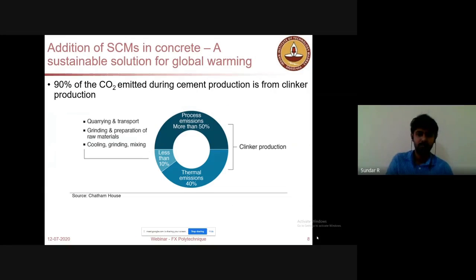So what are the choices? When you see how cement manufacturing contributes to the CO2 emission, there are three important processes. First, the limestone, which is a major raw material of the cement, expels CO2. When you treat the limestone at a higher temperature, the calcium carbonate expels CO2 and becomes CaO, lime, and then forms calcium silicate during cement production. That process itself emits almost 50% of the CO2 during cement manufacture.